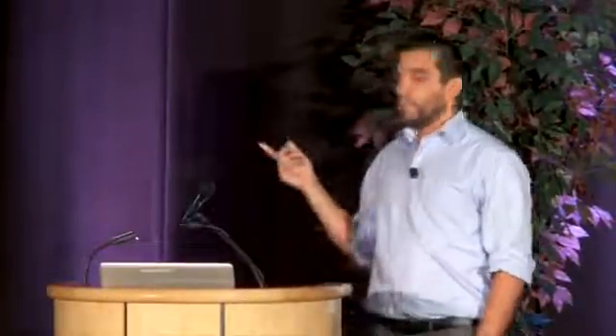And that actually leads to the other question I had. What do you think would happen to the self-healing system if you went to a 2C or a 5C charge rate? So it's actually terrible. I have the data. So 10C works, 5C, you see it at about 1,200 or so. And then when you go to 2C or 3C, it's below 500. So that's really a problem with this material.